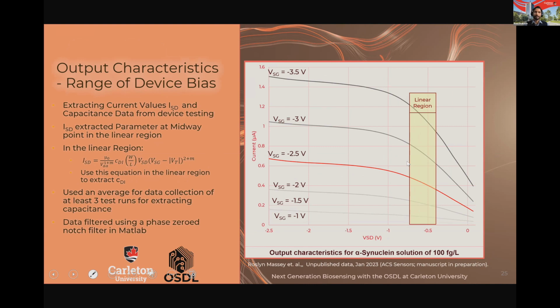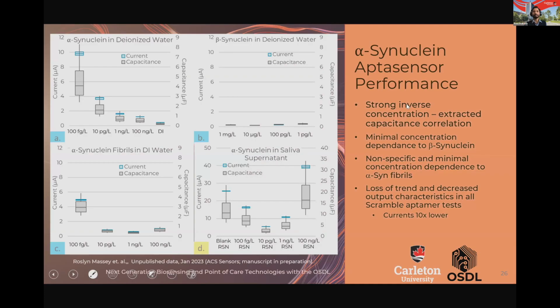And then you can see filtered data, which shows that you can modulate the amount of device current. This is sort of an electronic integration parameter. So how much current gives us reliable delta V for optimized readout and for reliable broad range sensitivity. So you can see that it's quite well correlated, and the performance is excellent. The signal to noise ratio is also quite high. The filter data establishes that.